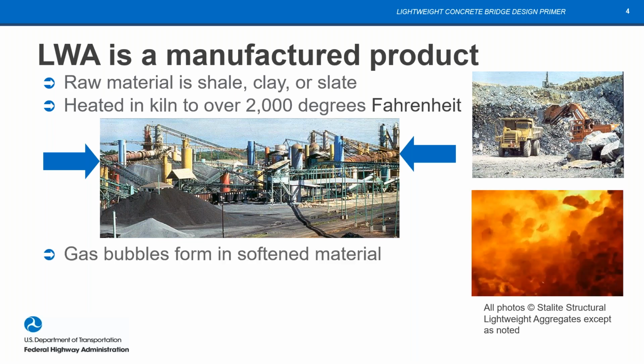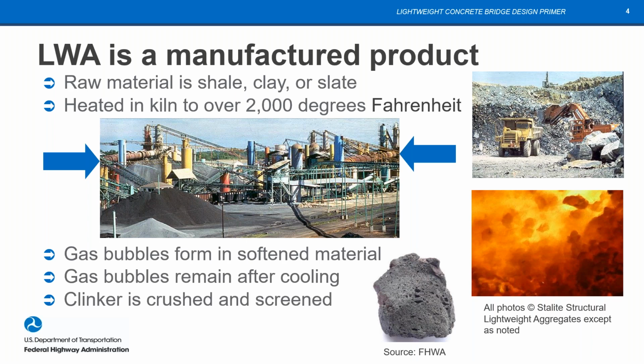It softens, doesn't melt, but it softens, and gas bubbles form in that material as it's softened, and then the gas bubbles remain after cooling. And you can see them here. It's a porous surface that you can see on the aggregate particles. The clinker is then typically crushed and screened. So that's how we get our lightweight aggregate.